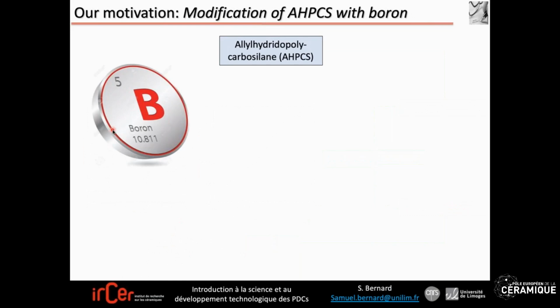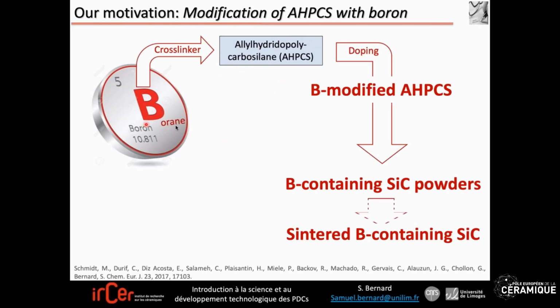We know that boron is a sintering additive of silicon carbide. Therefore, in our group, we consider the same preformed polymer to be modified with a borane, a low molecular weight compound, to form a boron-modified polycarbosilane, which is a real pre-ceramic polymer. Then it is pyrolyzed at a certain temperature to form boron-containing silicon carbide powders to be sintered later.